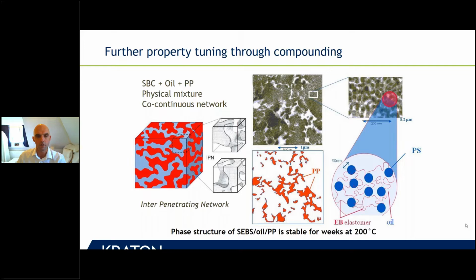and depending on the ratio of the different components, you get a different kind of morphology or micromorphology. What you're often looking for is an interpenetrating network because it gives a good combination of the two properties. But sometimes, of course, you're also looking to be a bit on the extreme side and have one component in the other. If you take out the polypropylene completely, you get an oil gel, and those are pretty solid materials. You would typically have something like 20% of styrenic block copolymer, and the rest is mineral oil, and those are all kinds of gel cushionings.